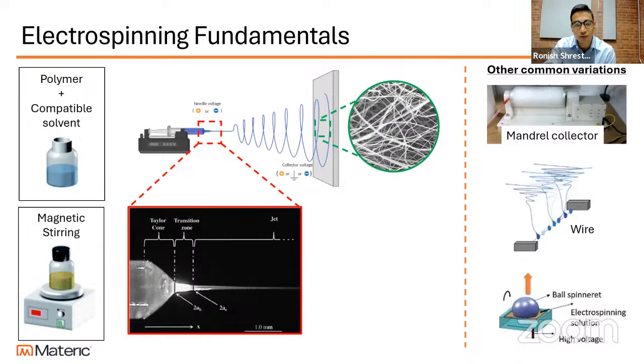So an electrical force is applied to the droplet of the polymer solution that is being extruded out from the syringe. That droplet has its own surface tension, and once the electric field is high enough that the surface tension of the droplet is overcome, it starts erupting into a jet in the form of a Taylor cone or a cone-like structure here. This jet, once it erupts, goes through a series of stretching and elongation, at which point the solvent that the polymer is dissolved in is also evaporating. So at the end, with enough stretching and elongation, you end up with ultrafine nanofibers of the polymer itself, which can range from tens of nanometers to a few micrometers in some cases.